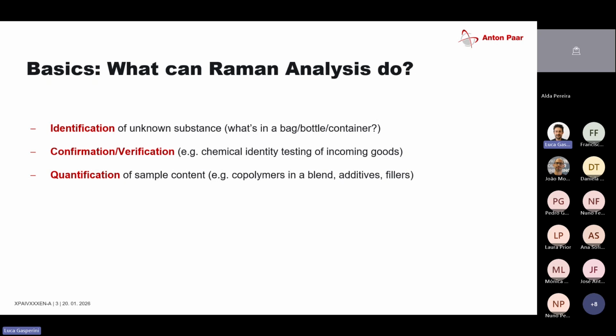Then on FTIR, it's very hard to actually quantify, let's say, the PC content in PMMA. The reason for that is that the spectra tend to overlap with each other. And then you would need some software in order to separate these peaks and actually quantify them. So this can be quite a struggle. This is where Raman is pretty useful. Because on Raman, on the other hand, you do not have that much information, so you only have a couple of peaks which typically do not overlap with each other.